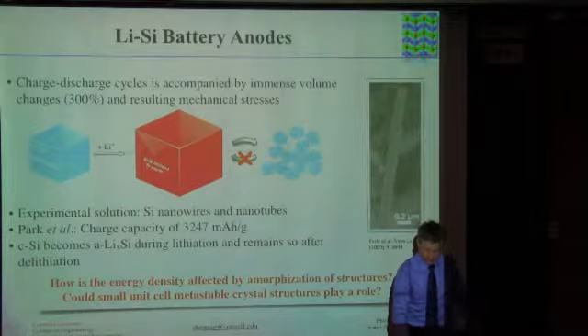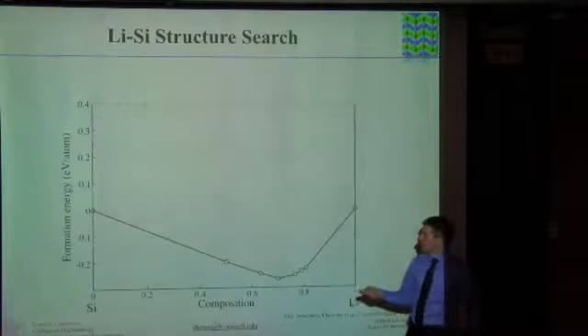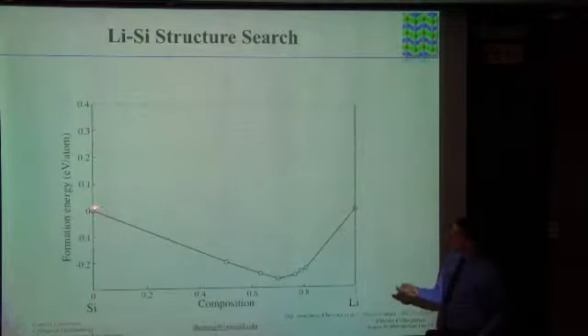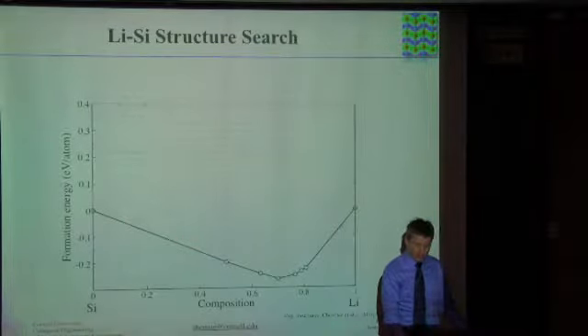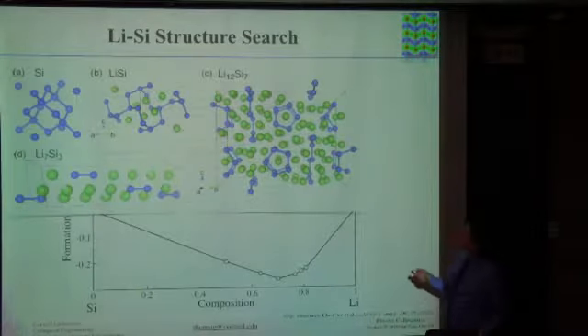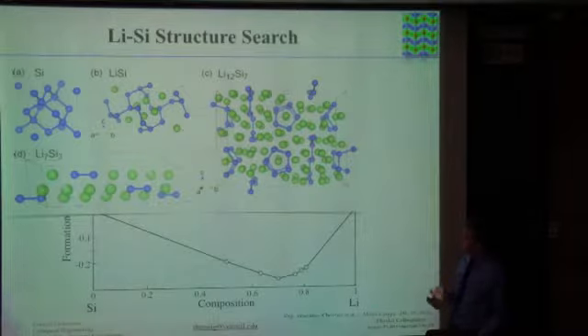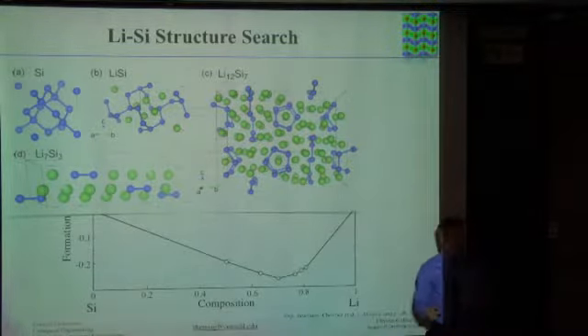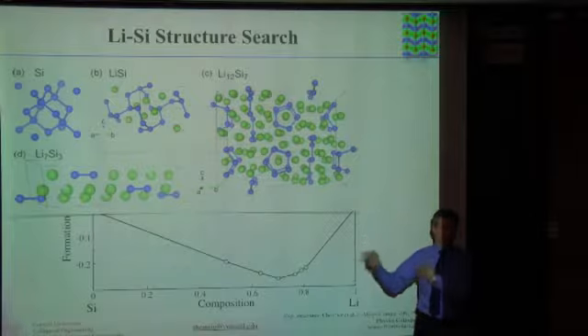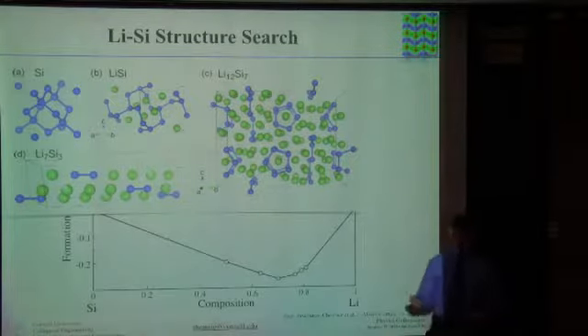So just saying the same thing here. So we look at lithium silicon. This is energy landscape for the known experimental crystal structures. So we just go through the literature, pick them all out. Silicon here, lithium here, and here's the energy landscape. Then we do so first of all I want to say these crystal structures are actually very interesting in themselves. They have very large unit cells. So here's, for example, lithium-12 silicon-7. It's very interesting, intriguing structures. We're not actually trying to discover those structures again. They're large unit cells. They're already known. Our algorithm is probably not very efficient in discovering what's already known, so we don't even try.